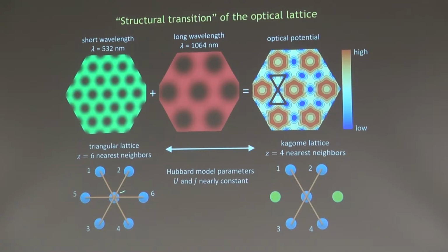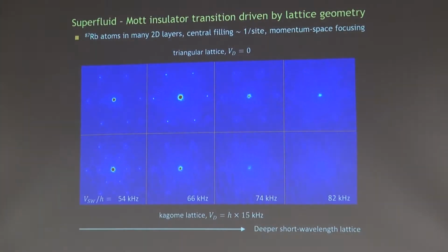And we have a lattice that can transition from one number of nearest neighbors to another. We can either study atoms in this triangular lattice where the coordination number is 6, or in the Kagome lattice where the coordination number is 4. So we expect perhaps some kind of transition to occur simply by changing the coordination number or the connectivity of the lattice. So we see that this is indeed the case.